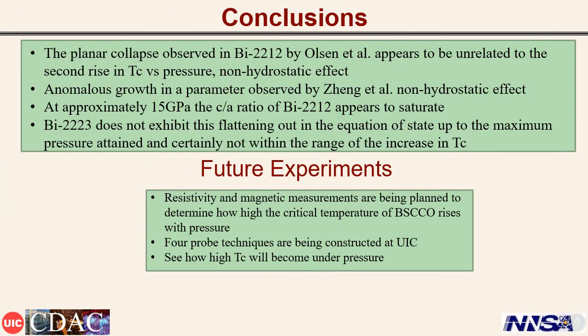The planar collapse observed in BSCCO 2212 by Olsen et al. appears to be unrelated to the second rise in Tc versus pressure, and is a non-hydrostatic effect. Any anomalous growths in parameters observed by Zheng et al. were also non-hydrostatic effects. At approximately 15 gigapascals, the C over A ratio of BSCCO 2212 appears to saturate.